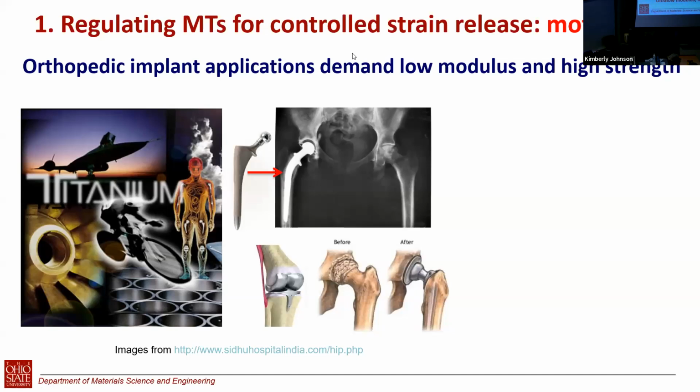So the idea is, if I can design a compositionally modulated material, you have niobium lean, niobium rich. They form this onion ring-like microstructure. Then when you apply a load or when you lower the temperature, you see here the niobium lean region. So I have the transformation occur at a pretty high temperature or at very low stress. This lean region cannot go too far because it is surrounded by the next layer, which has a different transformation temperature or stress.